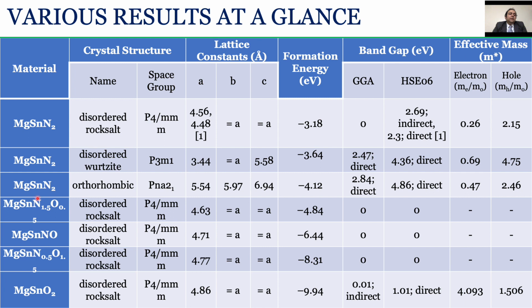We have prepared magnesium tin nitride in disordered rocksalt, disordered wurtzite, and orthorhombic crystal structures. We have also incorporated oxygen into the anionic sublattice in order to gauge oxygen contamination. The lattice constant for magnesium tin nitride in disordered rocksalt crystal structure has been calculated to be 4.56 angstrom, which closely matches the experimental result of 4.48 angstrom.